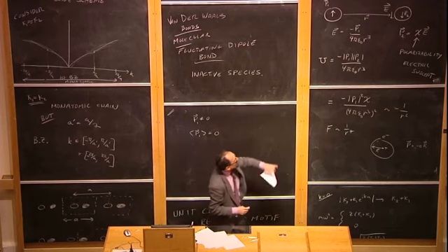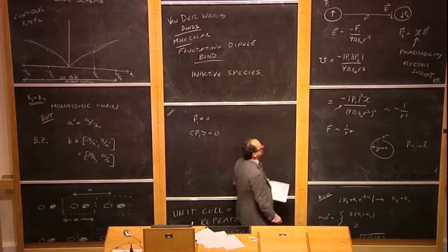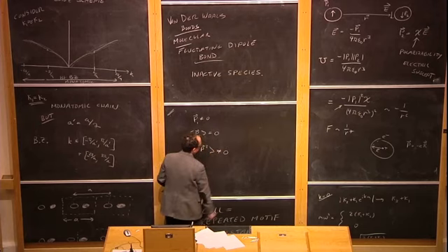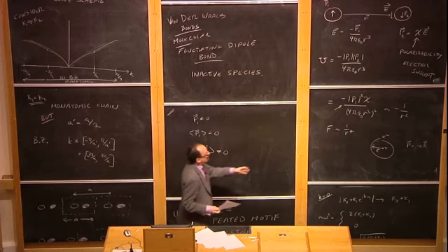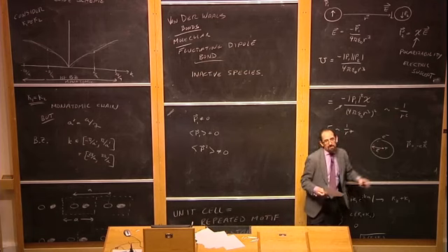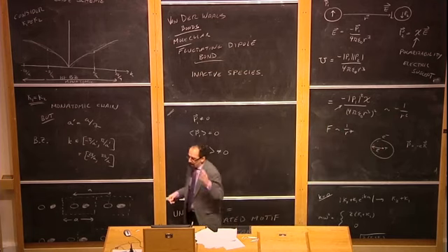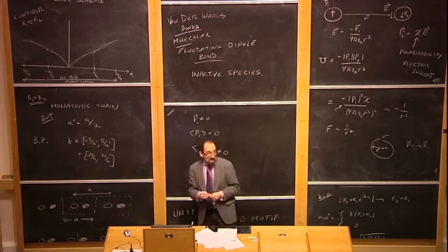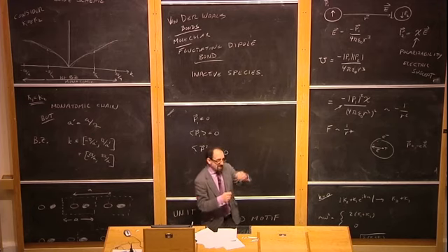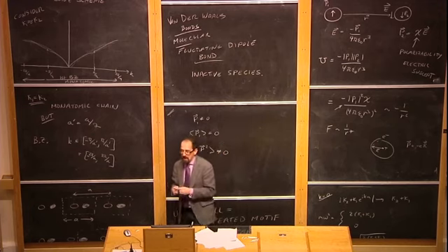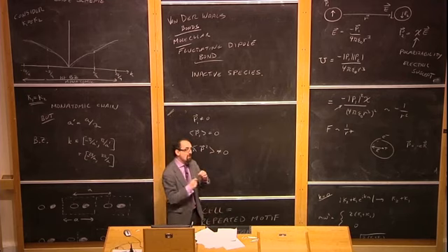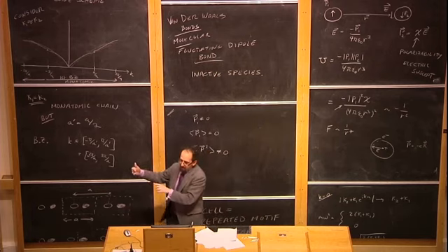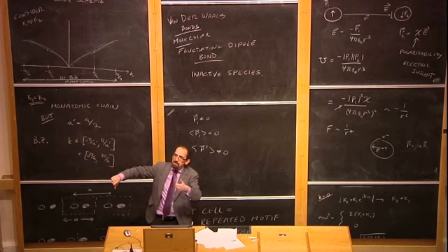But you'll notice that what actually comes into this equation is not the polarization or the dipole moment p, but it's p squared. So p squared is not equal to 0, so that you can get a non-zero dipolar attractive force, even though the average dipole moment is 0. If you like to think about fluctuations in quantum mechanics as some sort of dynamical fluctuation in time, that's a crude picture of what quantum mechanics is, but you can think of it as at some moment in time the electron is on one side of the nucleus, so there's a dipole moment. The other atom responds to that and orients its dipole moment in the opposite direction, and they attract.